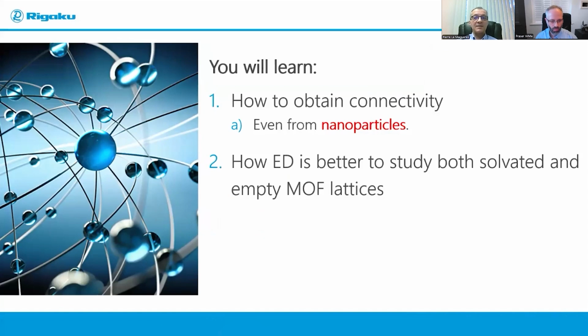And so Ross will also tell us how electron diffraction is better to study solvated and empty MOF lattices. Here, the thinking is really simple: the very fact that crystals for electron diffraction are so small also makes it easier to fully load them with guest molecules, because the diffusion pathways to the core of those small crystals are smaller, and also one can work with less guest molecule. So therefore, tiny crystals are better with electron diffraction to study solvated and empty MOF lattices.